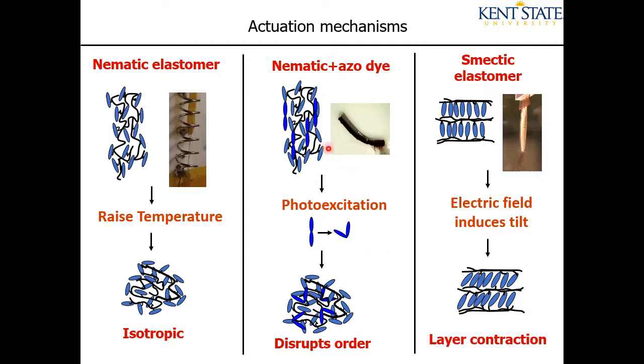Here's how that works. That material has been doped with a light-sensitive dye, an azobenzene derivative that has a photoisomerization. In its relaxed state, which is the trans state, it's kind of rod-like and more or less fits into the liquid crystal. But when it absorbs a photon of a specific wavelength that it's sensitive to, it will undergo a photoisomerization to an excited state, called the cis state, which is not rod-like at all. It disrupts the nematic order and causes the material to shrink. So this is a light-driven response.